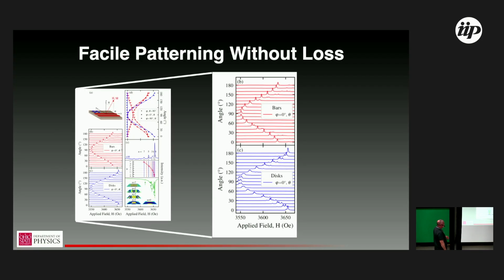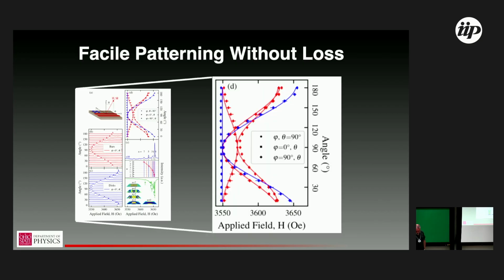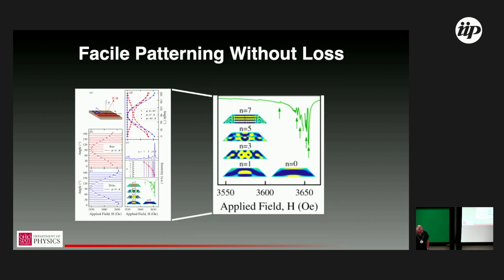This is just zooming, giving everybody the chance to actually see what's in this complex compilation here. And this is just talking about the flexibility that this gives us. So the way I like to think of this is we can make magnon resonators with arbitrary shape with control over anisotropies. Here is the in-plane to out-of-plane angle dependence of FMR for bars and disks. You can use this to extract the anisotropy parameters that take shape and crystal field into account very exactly. Those parameters then should fully predict the magnon spectrum of the material, and in fact they do. So I'll get to the analytic calculation in a second.